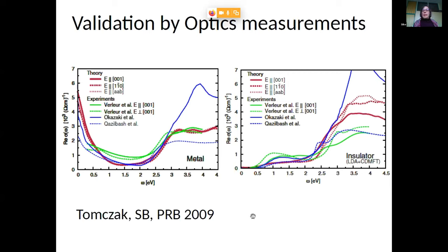If then you go to the insulating phase, you open up the gap here, and you have a little onset where you have optical transitions within the t2g manifolds, and then you really shoot up when the oxygens come in. And again, here, the theoretical curves in red and the experimental curves in blue and green are in reasonably good agreement.